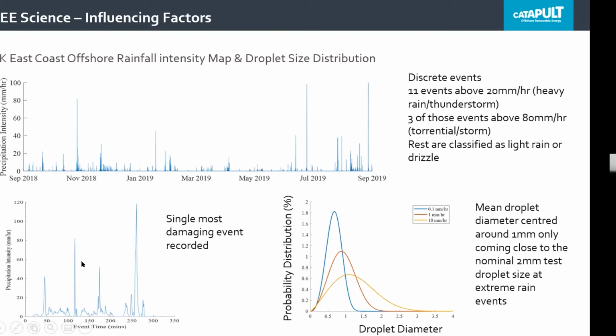I think the other thing I wanted to point out is that the rain changes. Although you can get very high precipitation intensities, what you'll see in the bottom left is that these generally only occur for really short periods of time. You will get a short high intensity period and then a really low intensity period. This is quite important, particularly when you're talking about polymeric materials, because polymeric materials can recover.